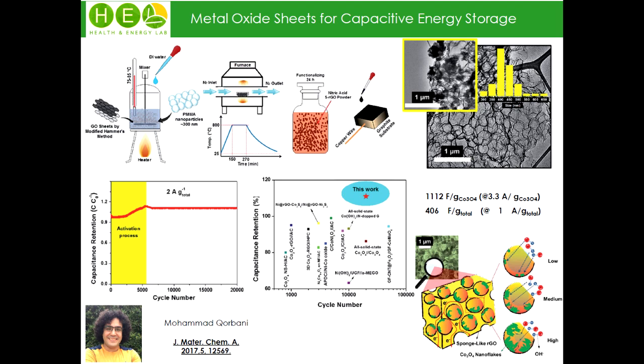So we changed the strategy, and now we designed another host for growth of cobalt oxide flakes. We synthesized a porous, sponge-like graphene skeleton, which is very conductive, using a template-assisted method with PMMA particles. Inside such a sponge-like structure, we again grew cobalt oxide nanoflakes—cobalt oxide and hydroxide composite phases, actually.